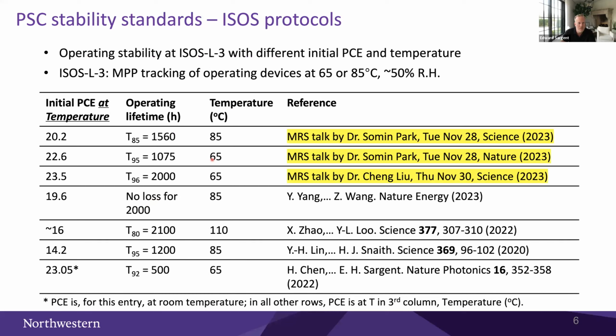So importantly, this high performance united with high stability is getting a very large amount of attention. And so you'll see here a summary of progress on the PCE at temperature. When I say at temperature, I mean these PCEs, which are a little lower than some of the headline numbers, they're a little lower because instead of operating near room temperature, these are actually operating at 85 or 65 degrees C. And you'll see a lot of interesting numbers here, exciting numbers in terms of operating lifetime in the 1 to 2,000 hour range. And the idea is to unite that with best available PCEs, which has been the focus of the field.